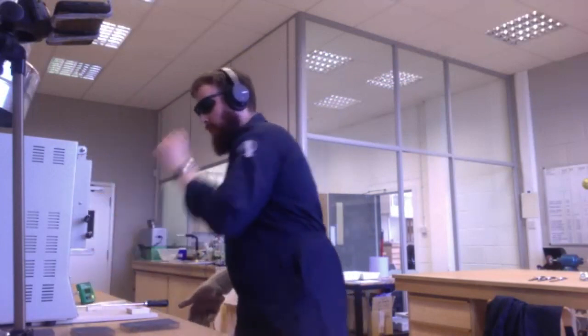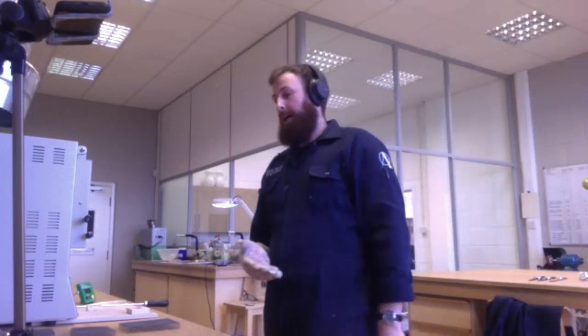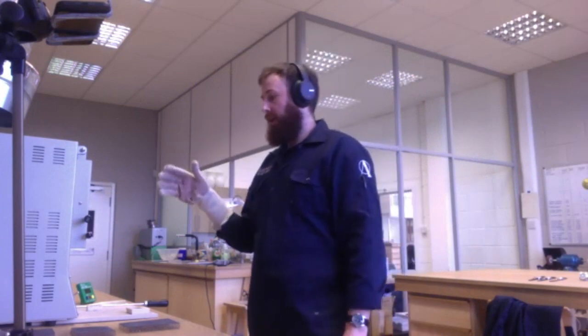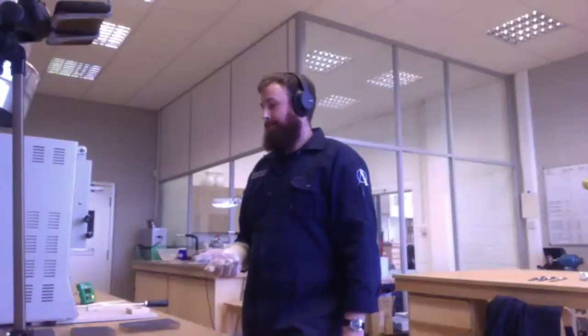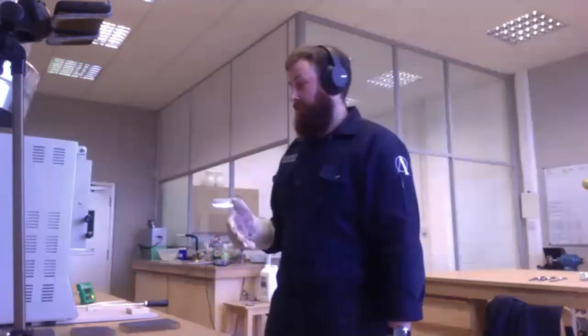What kind of temperature does the kiln run at? So we're generally running between 800 and 900 degrees Celsius. It does fluctuate. When you open the kiln, it drops. So you aim higher and work out how much it drops and then how long it takes to climb again. And we're generally only firing for between a minute and a half to 2 minutes maximum. So the firing's quick, but you then have to leave it and let it cool down. You can't touch it or fiddle with it, because you disturb it and it starts to do funny things that you then have to fix later on.